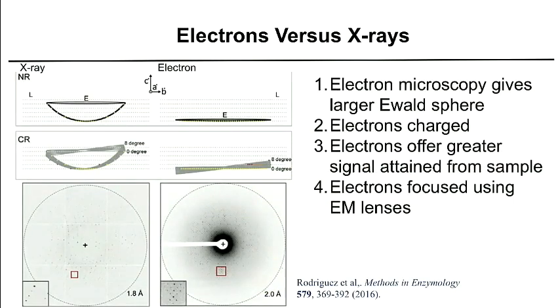The primary difference between electrons and X-rays is that the wavelength of electrons is on the order of 100 times smaller than that for X-rays, so the Ewald sphere is much bigger. In the panel on the left, you can see the curvature of the Ewald sphere. Upon performing continuous rotation, the intersection of the Ewald sphere with the reciprocal lattice gives spots in the diffraction pattern falling along lunes. Whereas for electrons, we're sampling the same area of reciprocal space, so the Ewald sphere is nearly flat.